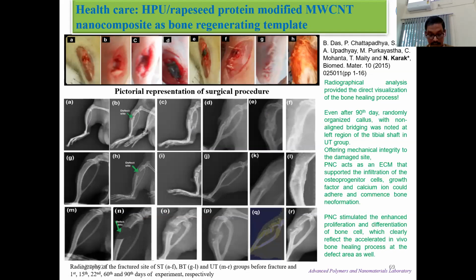One of the polymeric nanocomposites is used for bone regeneration as a scaffold. This is rapeseed protein modified multi-wall carbon nanotubes and sunflower oil-based hyperbranched polyurethane. I have shown photographs where we deliberately damaged the bone, on one side and both sides, of the Wistar rat. After application of this scaffold material, we observed bone regeneration, neoformation within 90 days, almost 100% in both cases. Whereas when there is no material, even after 90 days, there was no repair of the bone found. Thus, our material is really a scaffold material that can be used for regeneration of damaged bone. This was done with help of a medical doctor.